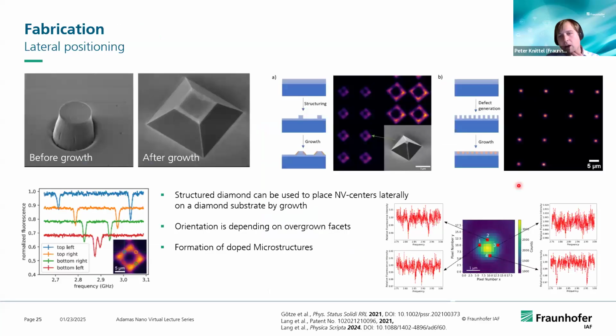And that's something we've seen a few years ago, that we can actually do our growth in a way that allows us to specifically dope on certain facets of a diamond microstructure. So what we've seen, or what is also depicted here, is if you have such a pillar structure that is etched and you overgrow this, so here what was done was an overgrowth first with an intrinsic layer, and due to this overgrowth, 111 facets form on the sides here. And adding a short additional growth containing nitrogen, you can specifically dope these 111 facets with NV centers.